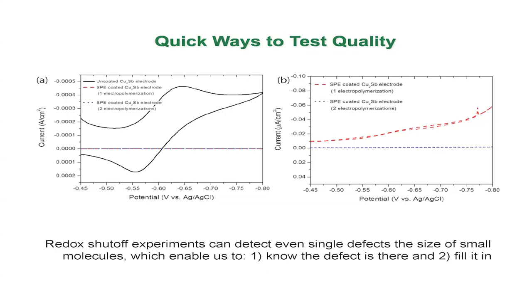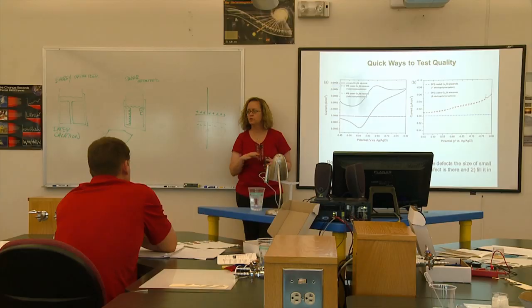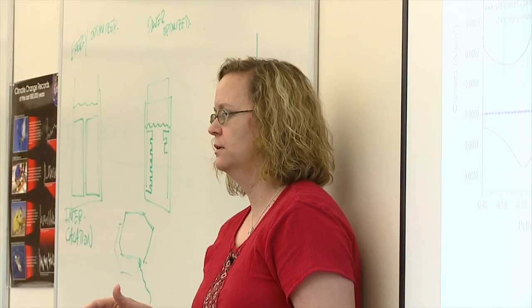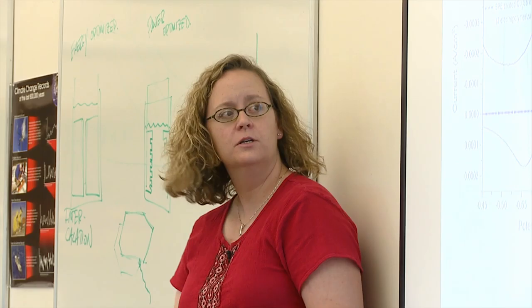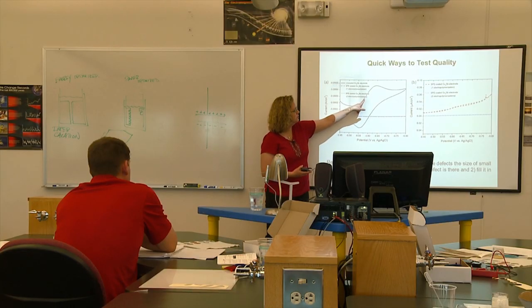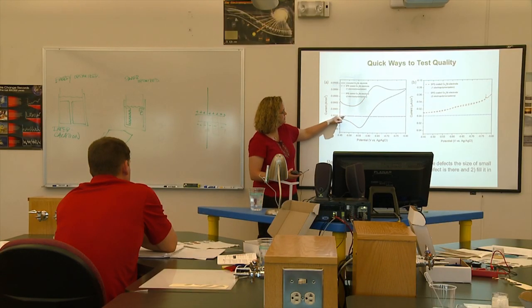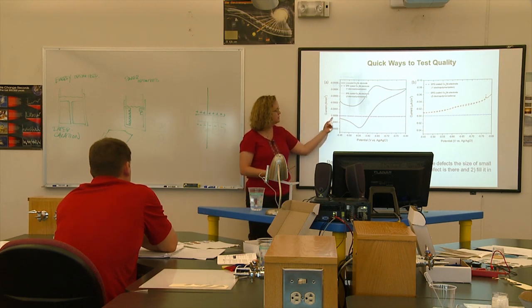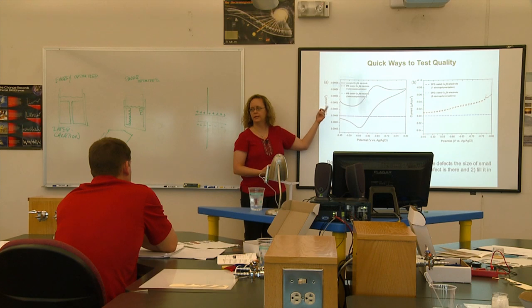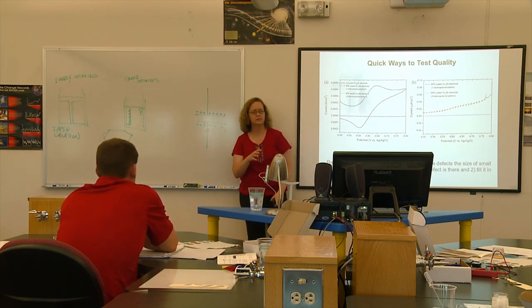So if there's a pinhole defect anywhere and we put this molecule in solution, that molecule should be able to get through that hole and we will see that duck shape. If there is no mistake, we shouldn't see anything. So we call this redox shutoff. So this is what it looks like on bare copper antimonide. And then these flat lines are what it looks like on our polymer after we've made it, which means there are no mistakes. We have really sensitive equipment. Notice the size of this current. We can actually go down to nanoamps, so we can go to 10 to the minus ninth. And it's super quick. This test takes 30 seconds.